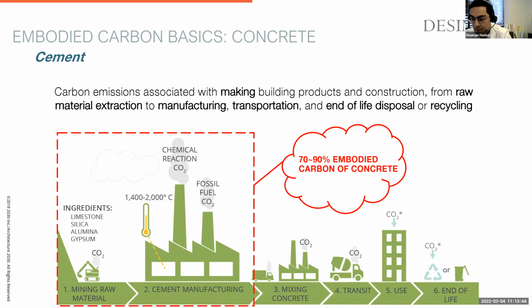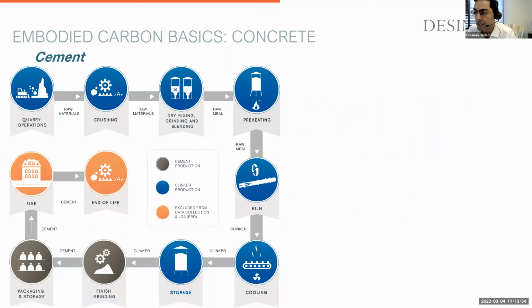The first two processes here, mining and cement manufacturing, are responsible for 70 to 90% of the embodied carbon of concrete overall. So let's dive a little bit into cement manufacturing. Cement manufacturing starts with raw material. You have to crush it, dry mix it, then you preheat it, and you have to cook it in a kiln, cool it down, store it, crush it, bag it, and then it goes to the customer. So it's a little bit similar to how you cook a steak, really, right? You pre-season it, then you take it out of the fridge so that it gets to room temperature, you cook it, you cool it down, and you eat it.